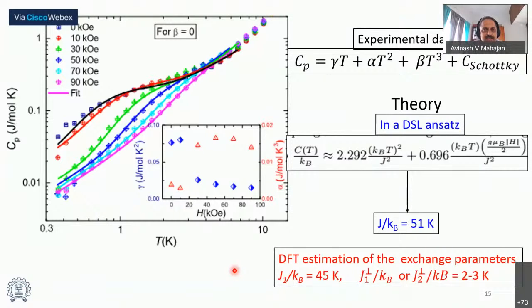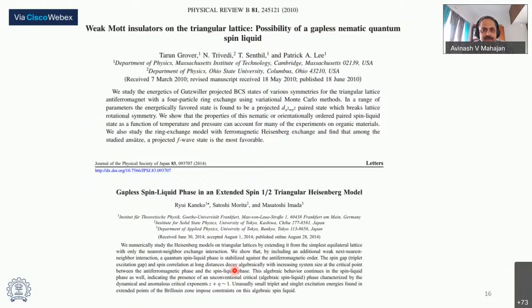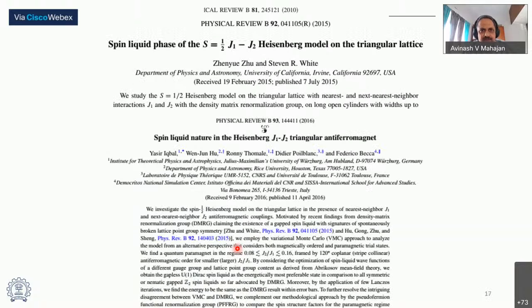So based on these, we suggest that you have a triangular lattice system, and perhaps there is importance of further interactions. So this is already suggested in some of the papers that were published earlier. So in a triangular lattice, there's a possibility of a ring exchange being present, and that might drive this kind of spin liquid behavior. This is another one where they're looking at not only the nearest neighbor, but further neighbor interaction, which can give rise to such spin liquid behavior.